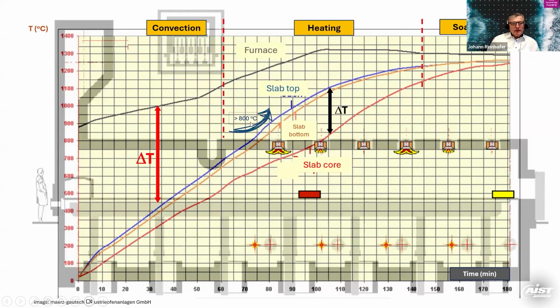That's the question. And then we say, okay, scale is not good. So we're in the range of, say, 1% scale from the steel weight for such a heating process. It can be 3%. For example, I saw 3% already in rotary hearth furnaces where you heat billets for a tube rolling mill, because you have a very high surface to volume ratio of these small billets which you're heating. On the one hand, this is an economical loss because you're losing material. I mean, you are burning steel, basically oxidizing steel. That gives also a little bit of heat, no? But steel, iron, is not a very good fuel in the end.